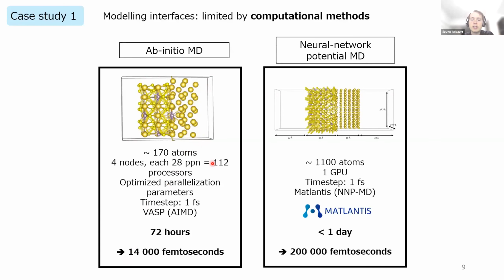And therefore, if we put this into contrast with looking at how Matlantis performs, here is a simulation file of around 1,100 atoms. Remember, Matlantis is able to simulate much larger systems, but in our paper, we had to study many different situations, many different conditions. So for that reason, we limited ourselves to 1,100 atoms, using only 1 GPU as part of the online calculation environment with an identical time step, and using Matlantis.